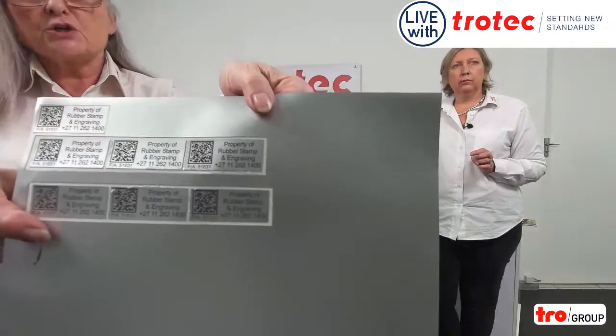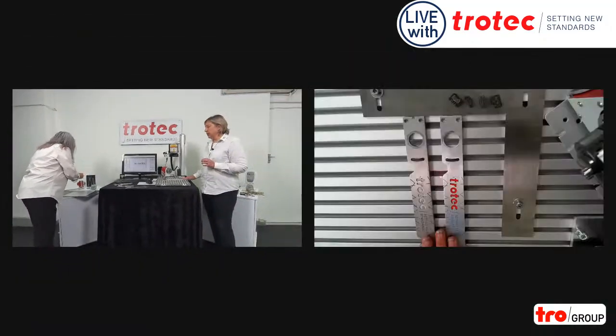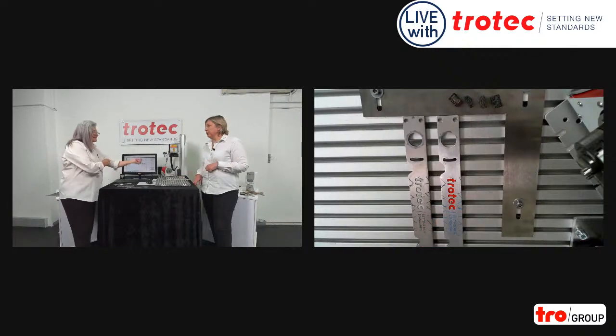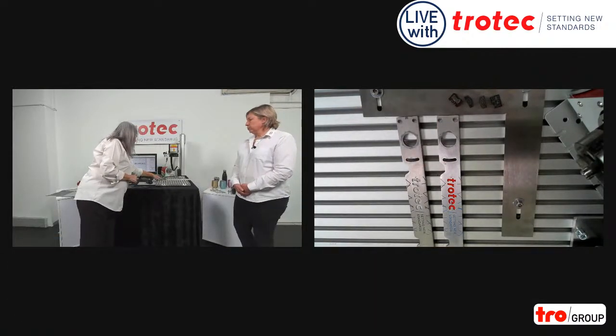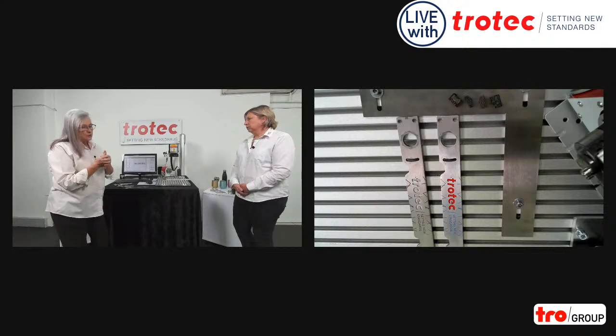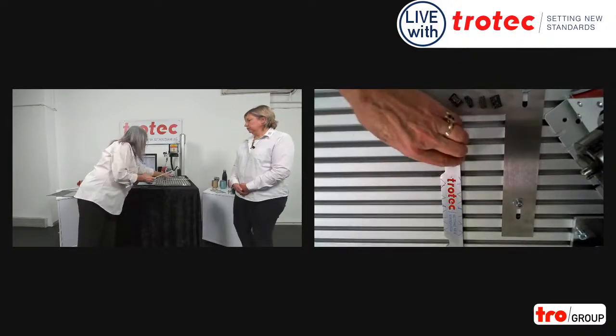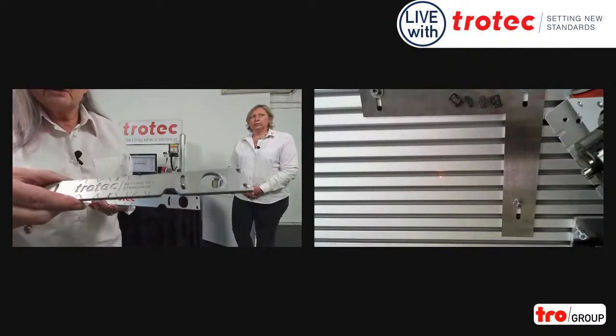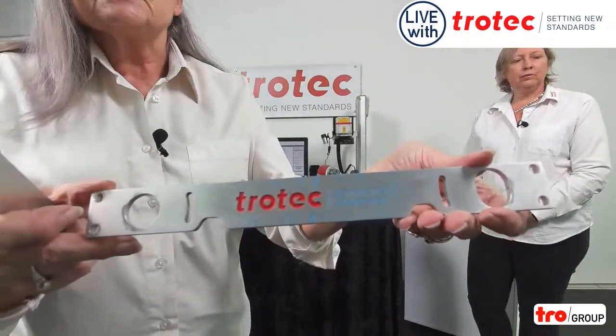So we spoke earlier about some deep engraving. We've placed it here so you can actually see it properly. What we've done is some deep engraving on aluminum. It can also be done on mild steel. Some very small items have been done. If it's something to make an embossing tool, you can do it in mild steel — but remember the heat treatment comes after, otherwise you will not mark it. If you're looking at the depth, you have the marking here with the line, and this is now when it's filled with different colors. The possibilities are endless at this level.